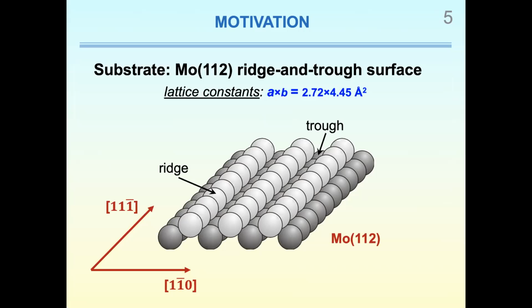And is all your plate uniformly covered by cerium? We cannot say that it's uniformly covered, but it should be, as much as you saw on this crystallographic schematic. Most of the surface is covered uniformly, but I guess at the border it can be slightly different. We have other publications about the profile of our deposited films, but here we assume that this is a uniform surface, a uniform film.